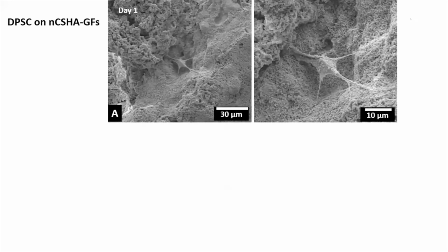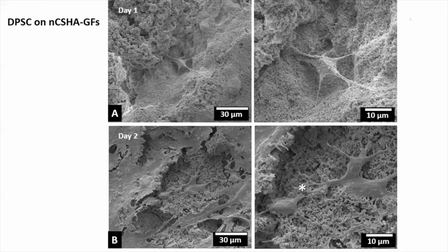This image is very interesting. The dental pulp stem cells were cultured on the scaffold, and we found that the stem cells would form a niche-like structure and grow on it. On the next day, we found that the dental pulp stem cells grew rapidly and the dendrites displayed projections and presented flat, well adhered to the substrate of the scaffold. And the formation of synapses between cells seems connected. This image also shows the cells like the scaffold very well.